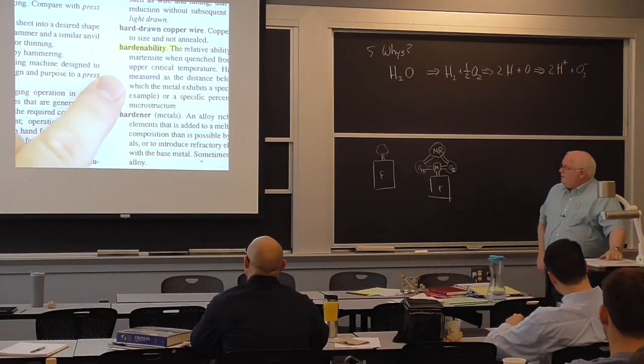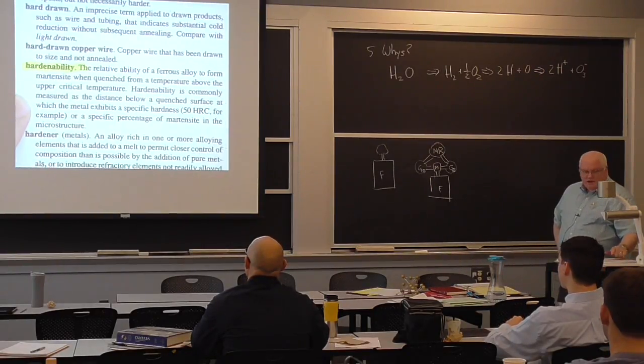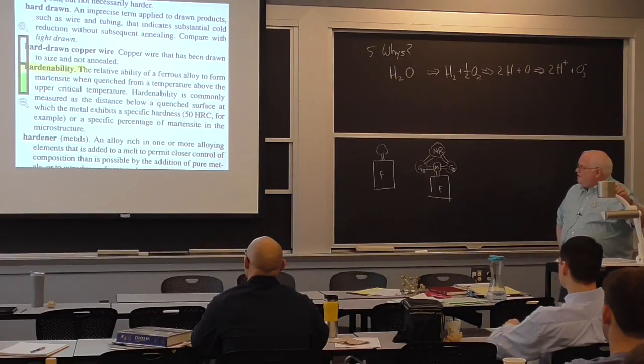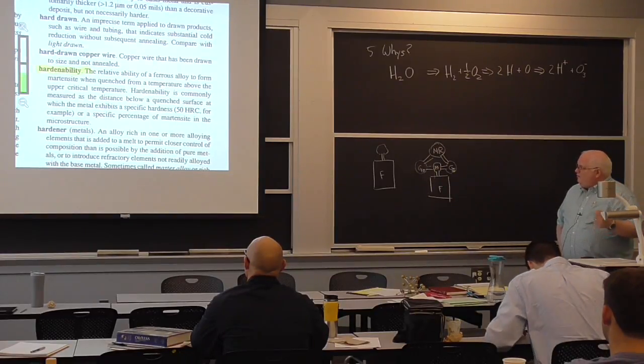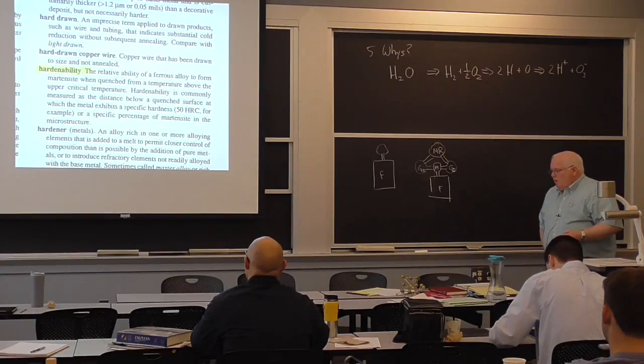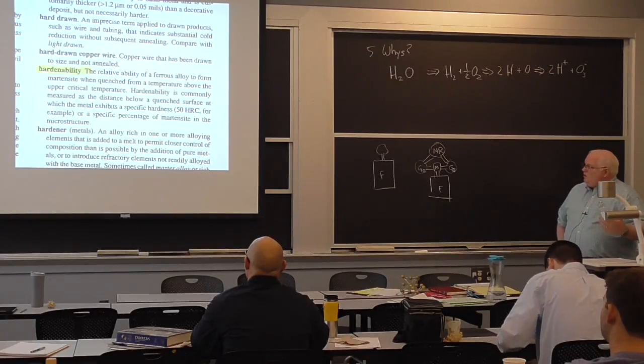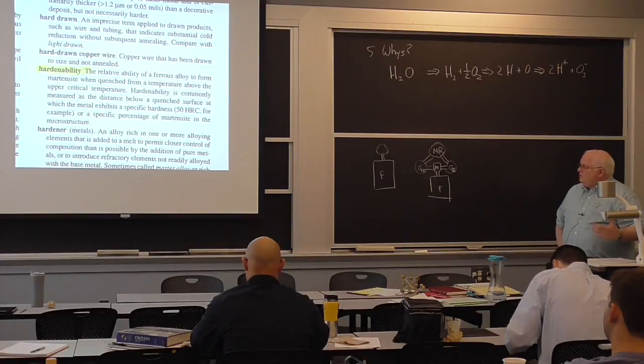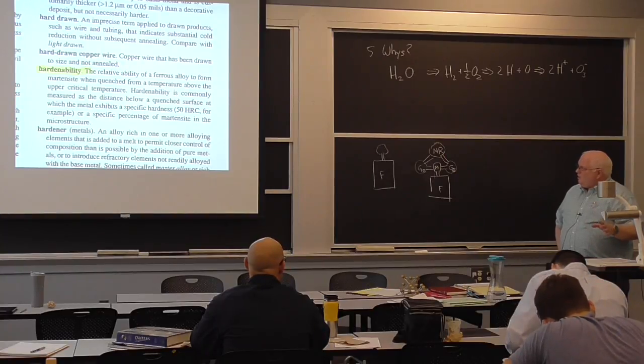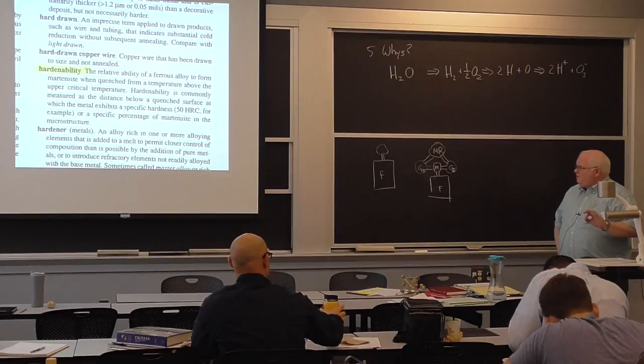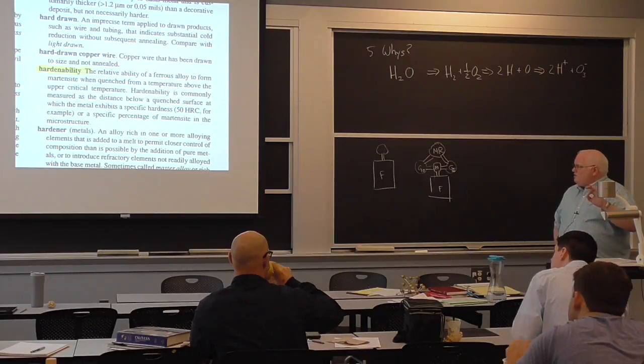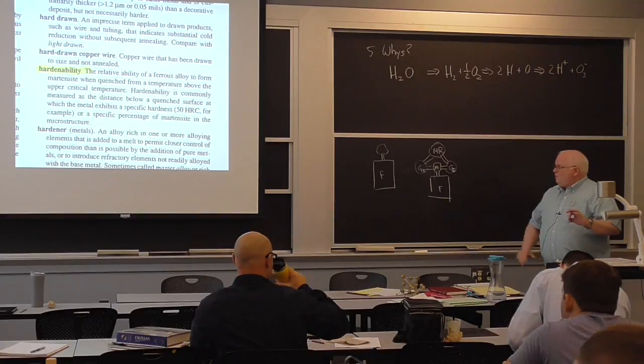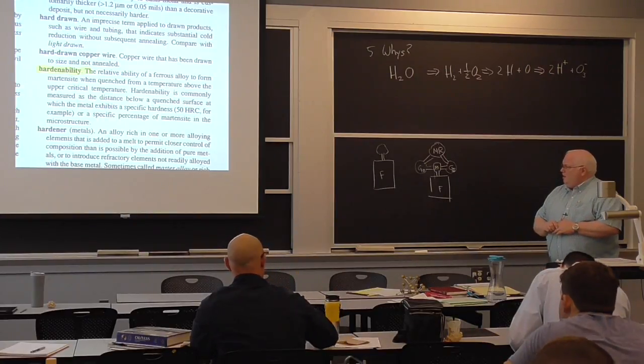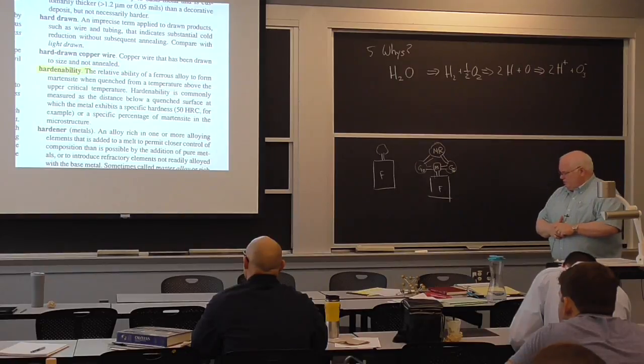Okay, so hardenability, on the other hand, instead of hardness, is actually different. It's the relative ability of a ferrous alloy to form martensite. What's martensite? Martensite is a particular crystal structure that is the really hard form that you get when you quench the steel. Okay? Martensite, when quenched from a temperature above the critical, I'll explain what that is in a second. Hardenability is commonly measured as the distance below a quenched surface at which the metal exhibits a specific hardness, like 50 Rockwell C, which is HRC, for example, or a specific percentage of martensite in the microstructure.